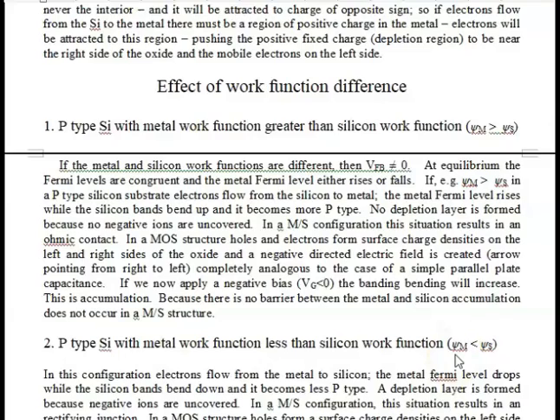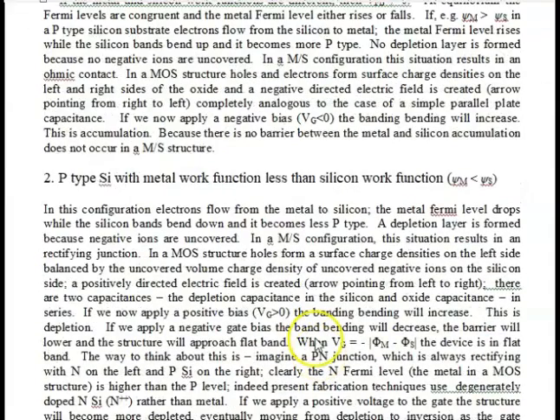And that's the second case we're looking at, where the metal work function is less than the silicon work function in p-type. In that case, we start out at equilibrium with no gate bias in depletion. If we apply a negative gate bias, then we can go to flat band, and then eventually, if we continue to increase the gate voltage in the negative direction, make it more and more negative, we can go into accumulation. So the flat band voltage will always be negative, and here it's just equal to the magnitude of the difference between the work functions.